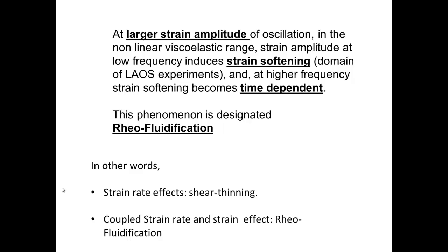And if one uses higher frequency, as we will see, strain softening becomes time dependent. This phenomenon I call rheo-fluidification. In other words, to describe strain rate effects, we'll still use the classical term shear thinning, but if we couple strain rate or frequency and strain effect, we call that rheo-fluidification.